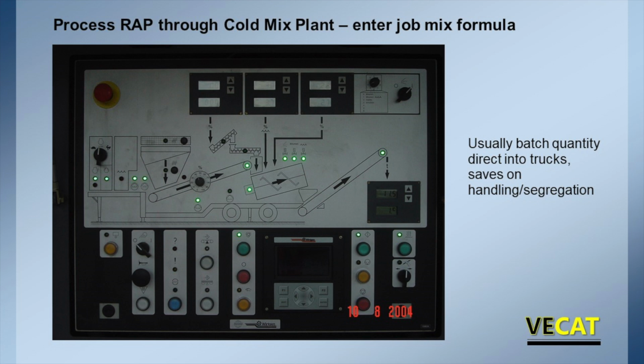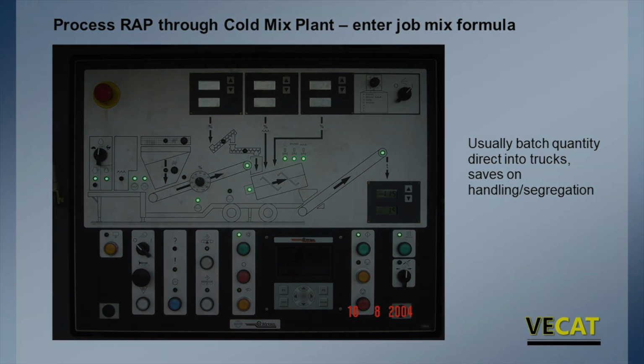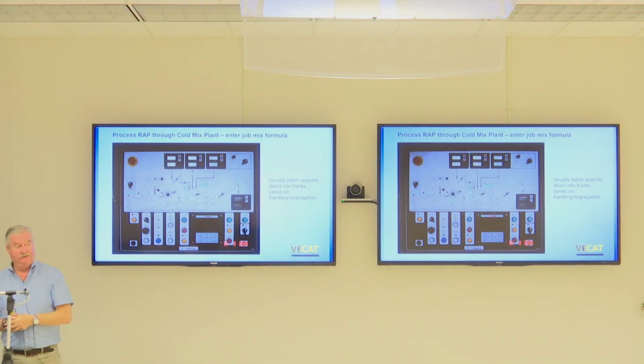But the important thing is here, these three entry points are where you'll put in your mix design. So the lab will give you the design parameters for that mix. If it's 100% RAP, typically you'll be putting in 1% cement, 2.2, 2.5% foamed asphalt, or 3.3% emulsion, and then water for compaction. Water for compaction is a variable. That should be your only variable when you're operating the plant. These two items, binders, are fixed by the mix design, but your moisture that you're adding is for compaction.